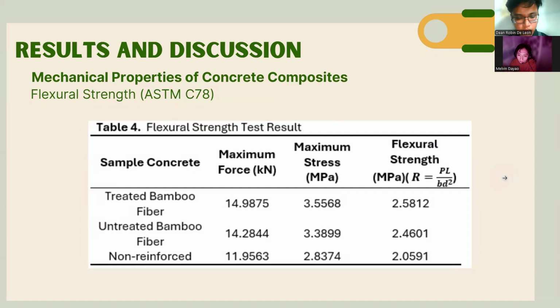For the flexural strength, treated bamboo fiber reinforced concrete exhibited the highest performance with a maximum force of 14.98 kilonewton, a maximum stress of 3.56 megapascals, and a calculated flexural strength of 2.58 megapascals. This represents an increase in flexural strength compared to the untreated fiber reinforced concrete and non-reinforced concrete, which had a flexural strength of 2.46 megapascals and 2.06 megapascals respectively.